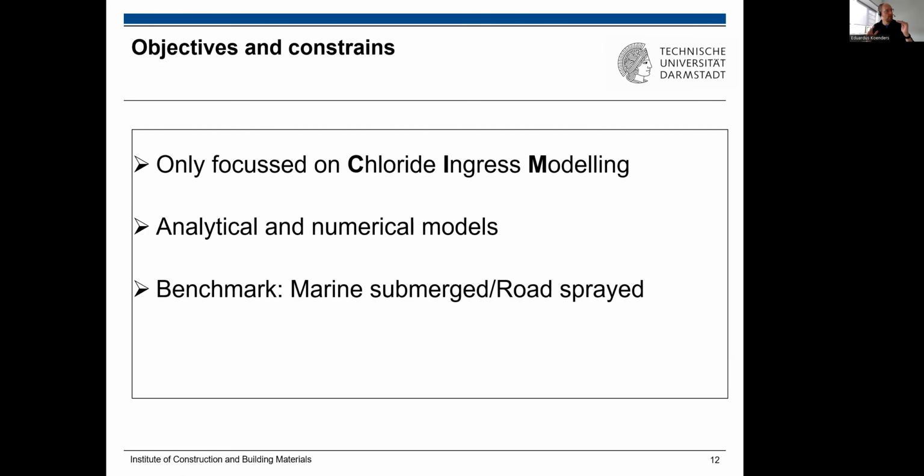Analytical models actually have an infinite space. You cannot use analytical models for a very thin concrete panel which is submerged in water and has a chloride load from two sides, because the chloride profiles will start to influence each other. They will overlap in the middle. So those things have to be taken into account. Finally, we selected two benchmarks, the marine submerged and the road spray, as the basic benchmark cases.